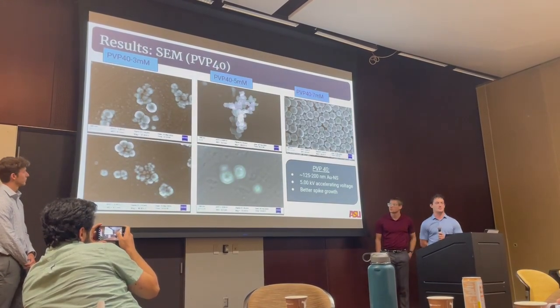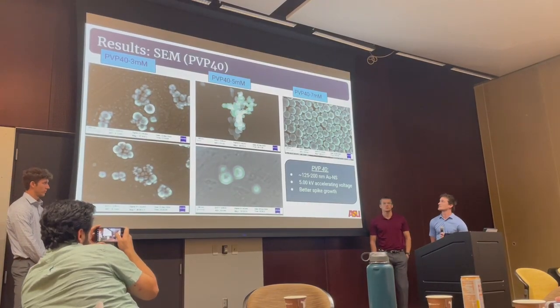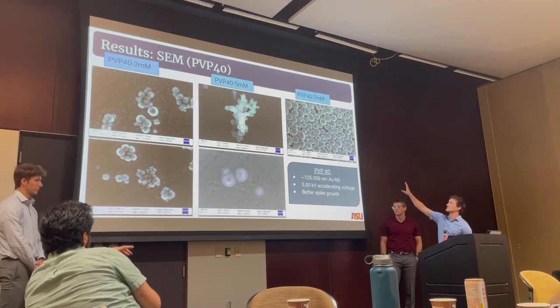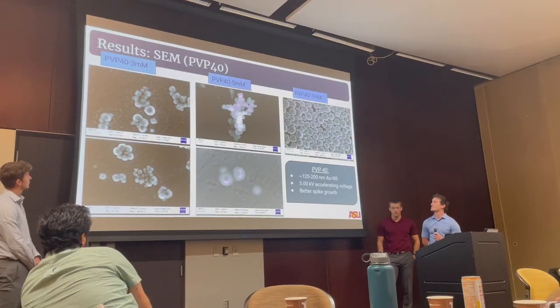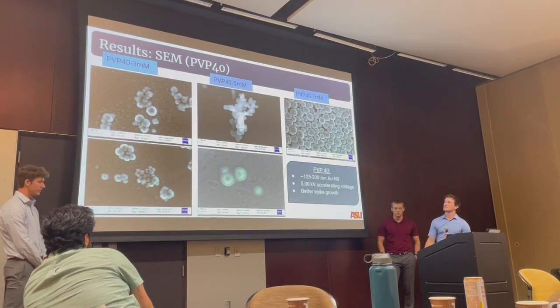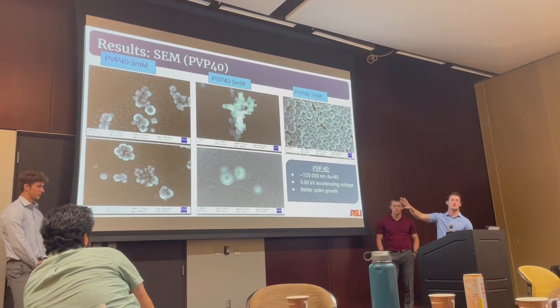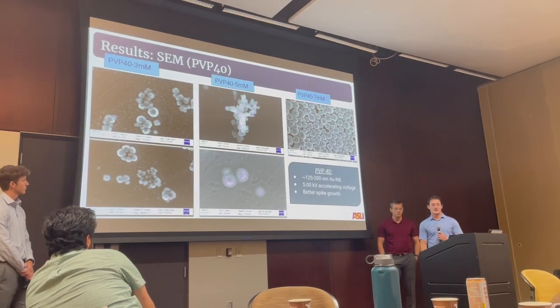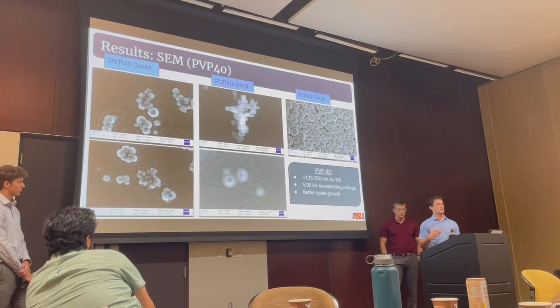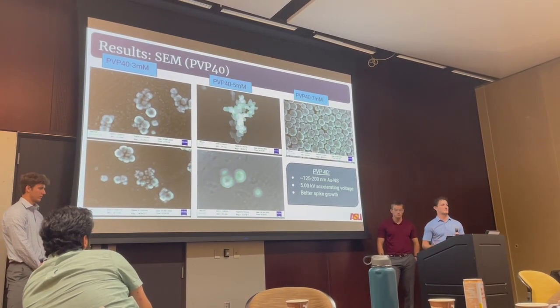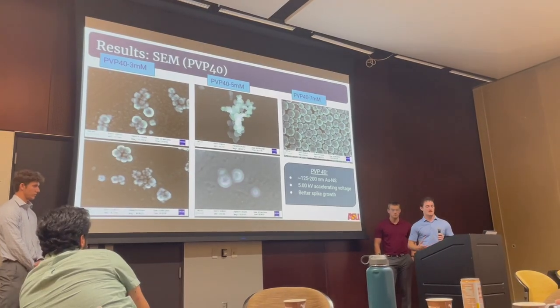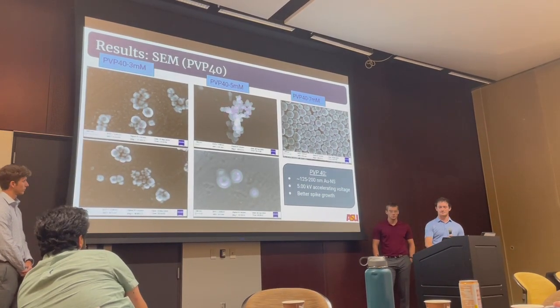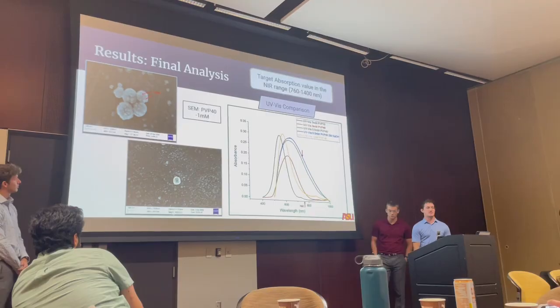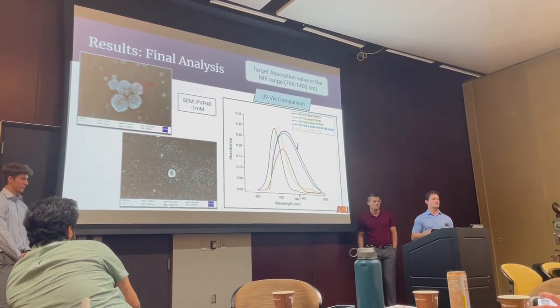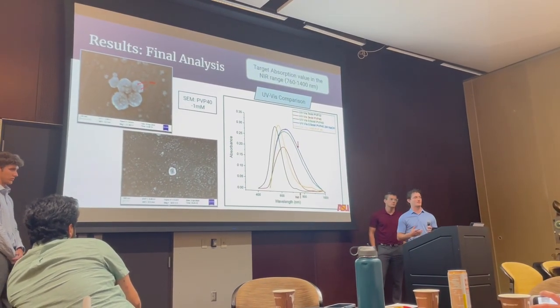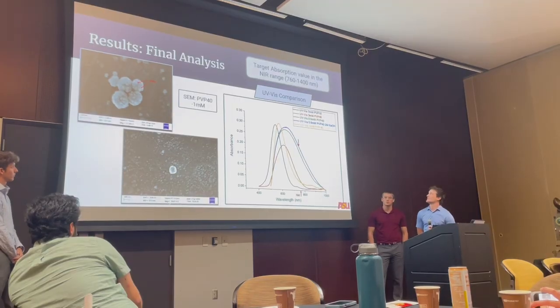Then we moved on to our PVP-40, where we started to get some better data. You can see really clearly in the 7 millimole PVP-40 branches starting to form, and you can also see them in the 3 millimole, they're just not as clear in the imaging. Our nanoparticles also got bigger with the PVP-40, which allowed for a higher absorbance rate, and we had better spike growth as well. So once we had decided that PVP-40 was the route we wanted to go,